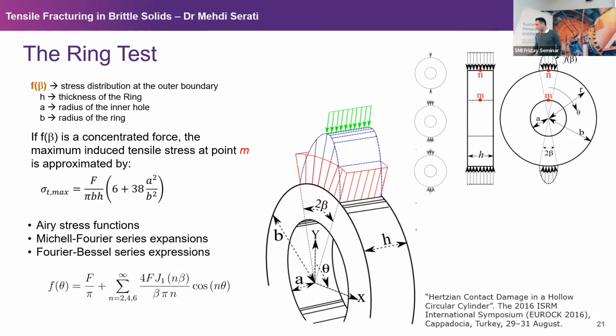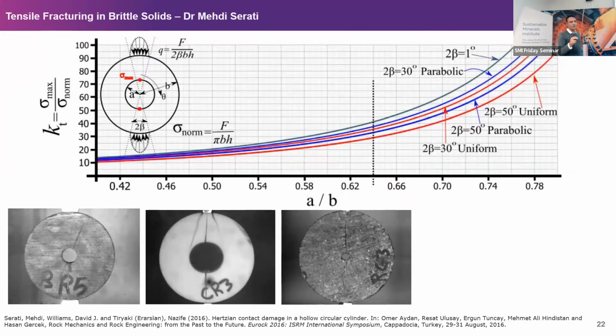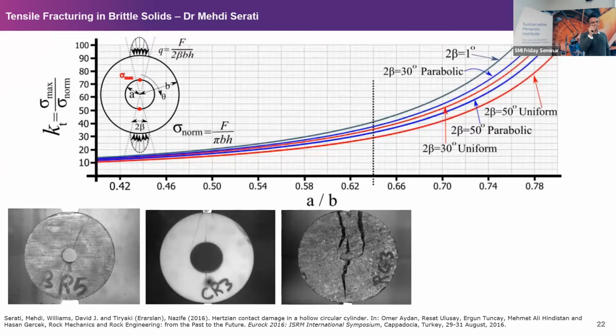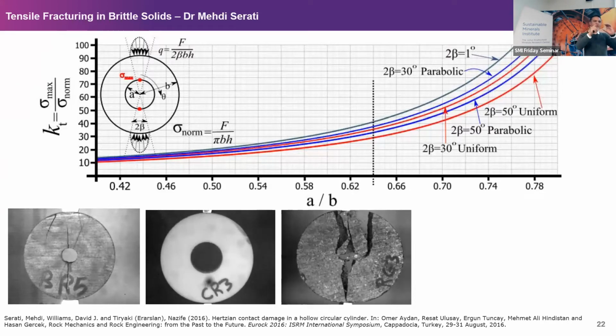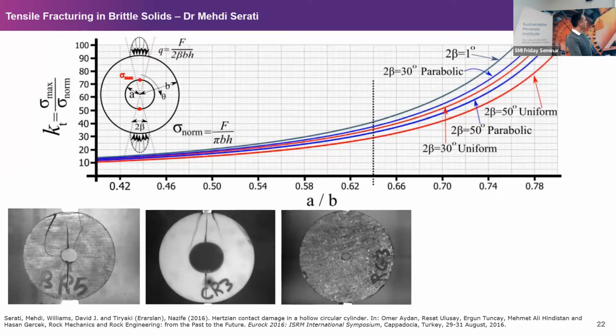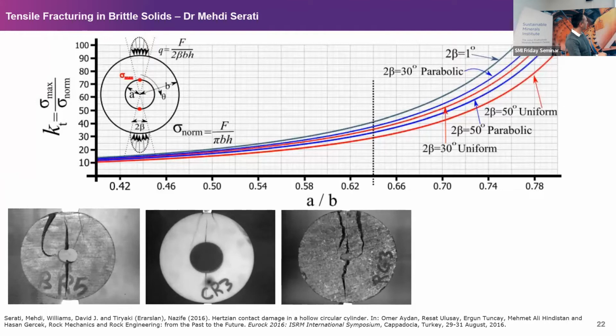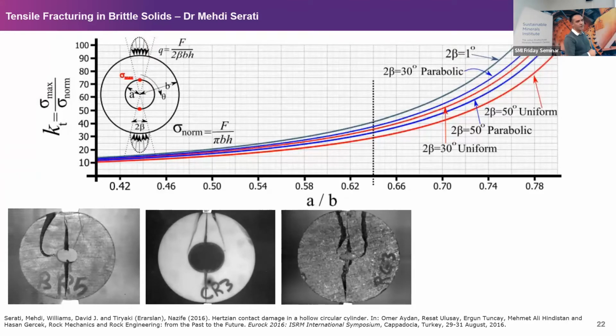But if you have done the ring test, and I'm quite sure that you are experts, you might have noticed that in some cases, depending on the ratio of the hole to the diameter of the disc itself, not only do you get this tensile crack, but sometimes you also get a tensile crack in this direction.